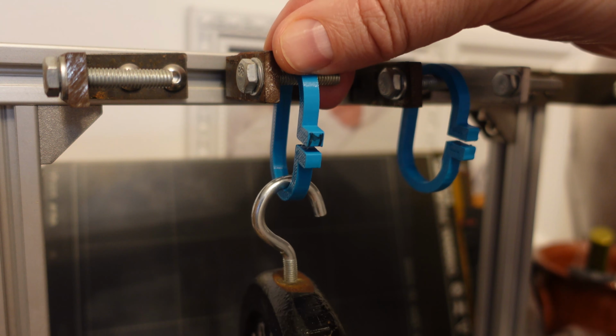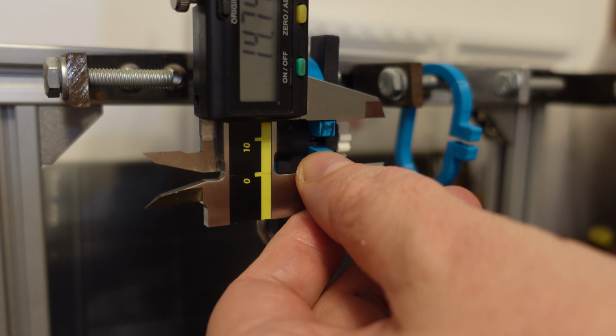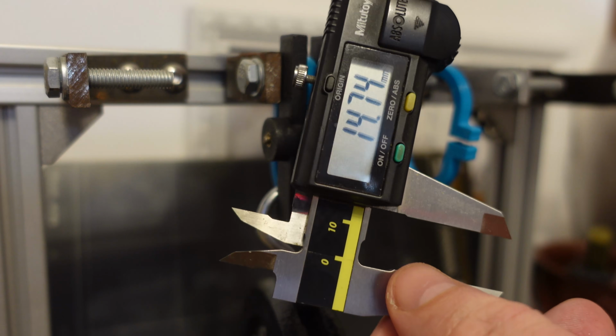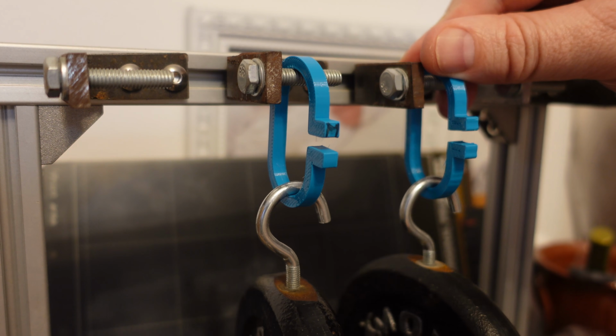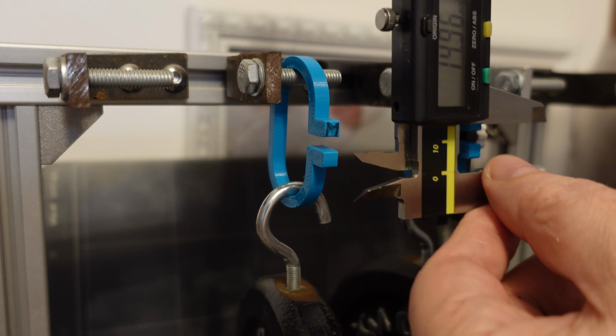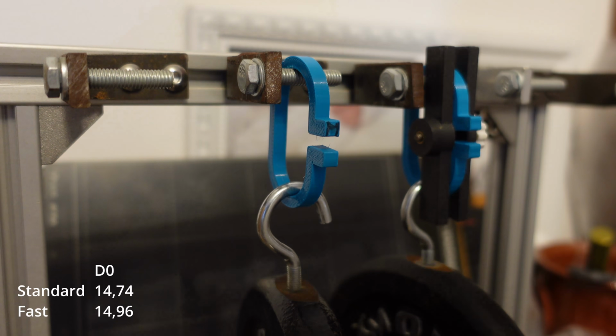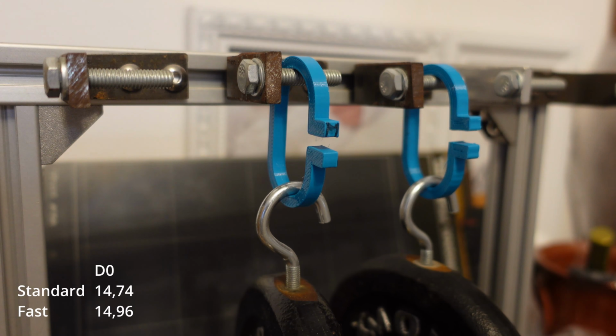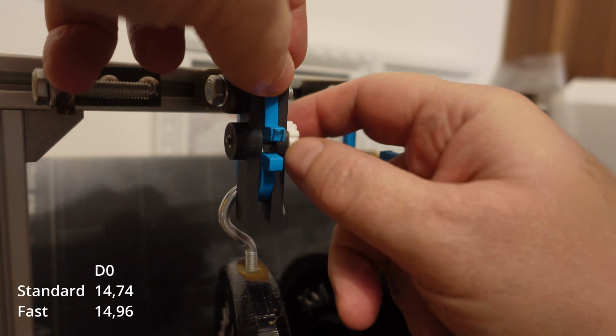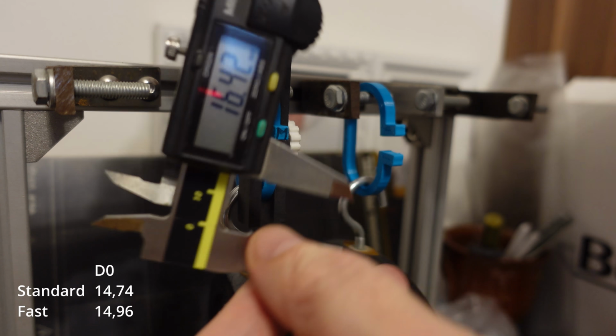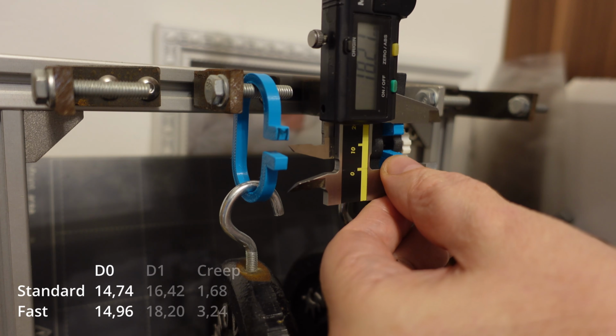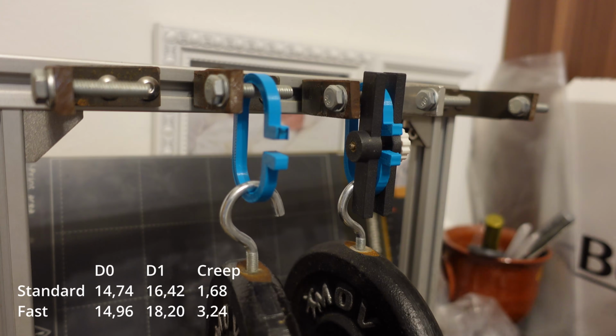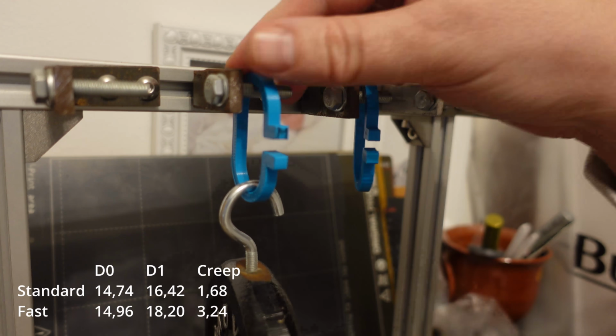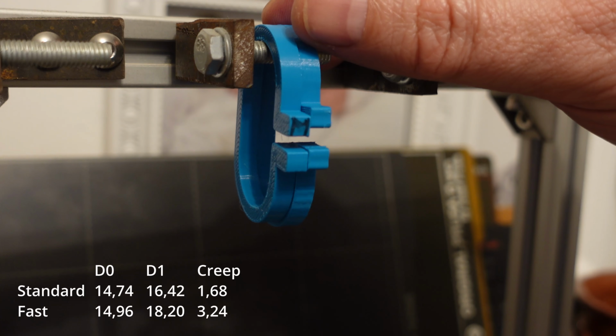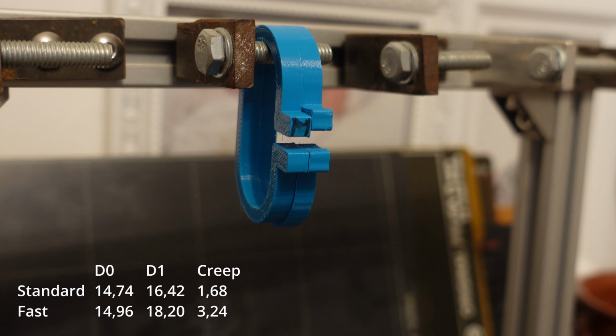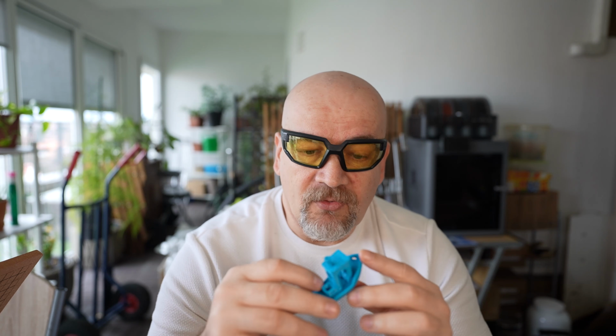Creep is a deformation under constant load, not so important for this material, but I have the test object, so let's measure it. 14.74, and printed fast 14.96. Not a big difference, but a little bit more deformation on fast printing. And after 1 day, printed on standard speed 16.42. And the fast printing version 18.20. More creeping. Actually, in this case, the adhesion between the walls is important, and yes, more deformation on the fast printed version. Okay, now some kind of conclusions.